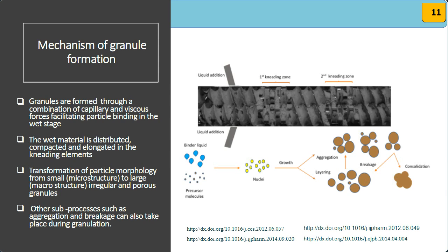On this schematic graph on the right side, we can see how they are formed, and we can get an idea of the granule mechanism. We start with the binder liquid, where we have the precursor molecules. We see the creation of nuclei in the first kneading zone, followed by the growth of the granules, aggregation, layering, or breakage, and eventually the consolidation, which usually takes place after the kneading zone.